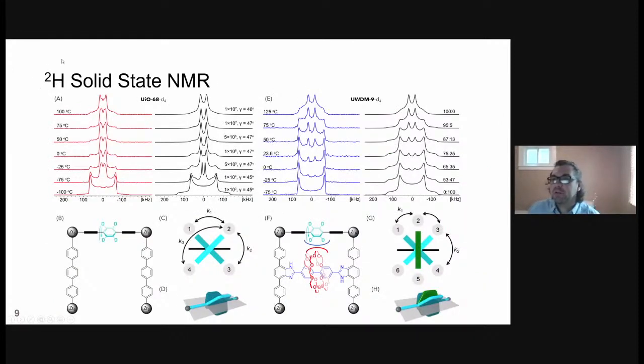deuterium solid state NMR, as this technique is very sensitive to the rotation of deuterium nuclei. So it's really useful for characterizing these types of molecular rotors in MOFs. So what we did is we conducted VT measurements on both UiO-68 with this deuterated coligand and UWDM9 with this deuterated coligand and this cross-linking rotaxane linker. And so when we carried out these deuterium NMR experiments, we could see significant changes in the NMR spectra upon going from UiO-68 to UWDM9-D4.